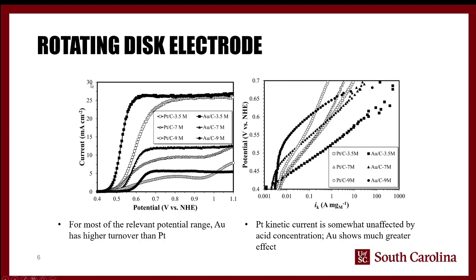And so the second thing that's apparent is that gold in all cases outperforms platinum. The difference between the two does get less as you increase your sulfuric acid concentration, but in pretty much every case, the limiting current is higher at a lower potential, and that's what we're looking for.